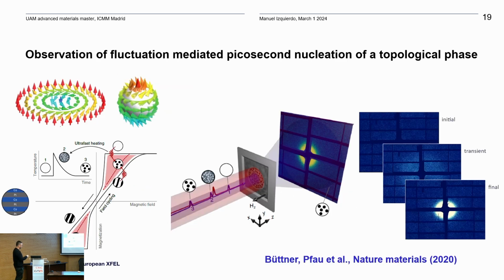Okay, so one of the experiments that has been done with this is using small angle X-ray scattering to study the formation of skyrmions in this cobalt platinum multilayer. This is the hysteresis curve of this compound, and what happens is that you start from a homogeneous phase, and if you have enough energy, you are able to go into an excited state, and from there to produce skyrmions.